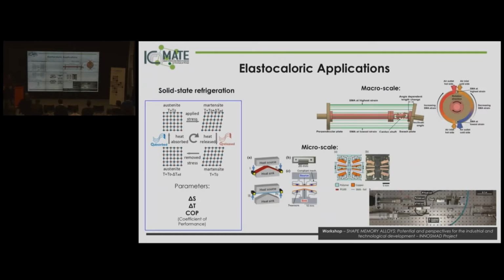Other applications regard the elastocaloric effect, which exploits the ability of the shape memory alloy material to release heat and absorb heat when stress is applied adiabatically on the SMA material. There are some solutions that have been developed both on the macro and the micro scale, with the material in the form of wires or sheets or ribbons and so on, which is periodically deformed, and the heat that is generated is sunk into maybe a refrigeration system. In fact, these elastocaloric applications are now studied, and they regard principally solid state refrigeration, as Elena said before.